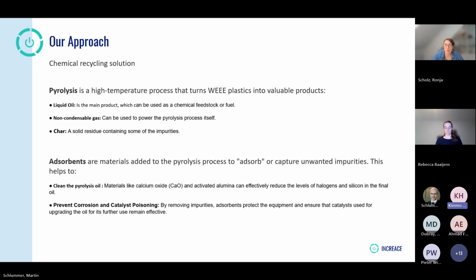Then, the products from the pyrolysis: the main product is liquid oil, and then there is gas, which usually can be utilized in the pyrolysis to heat the process, and then char. Depending on the quality of the feedstock, char can be from 5 to 15 to 20%, for example if we feed a lot of glass fiber containing plastics, then we get a lot of char. But if we have non-filled plastics, the char content can be very low also. And adsorbent is mentioned here because we studied also the utilization of adsorbent materials in the pyrolysis. We will have some results from those soon. So, next slide.